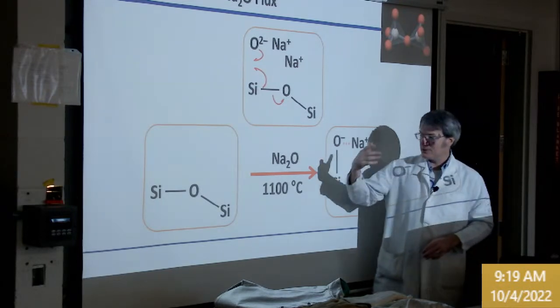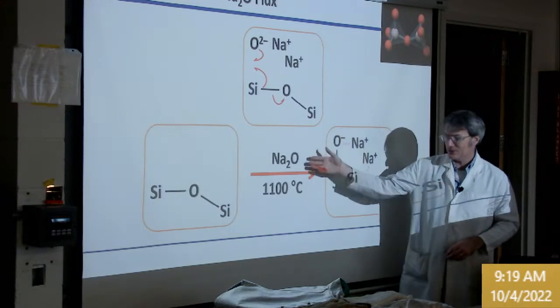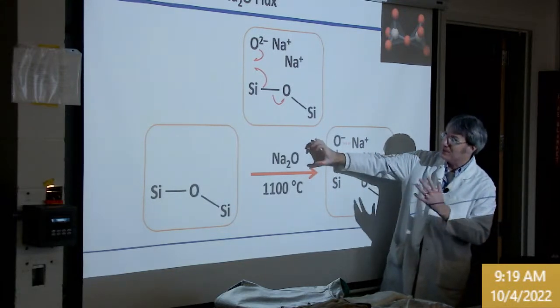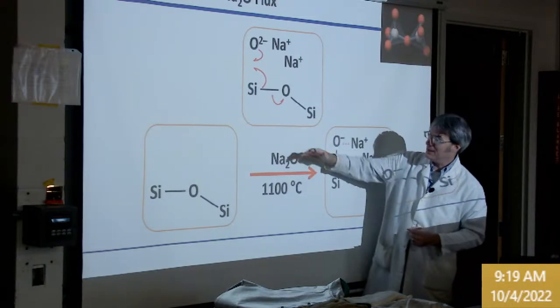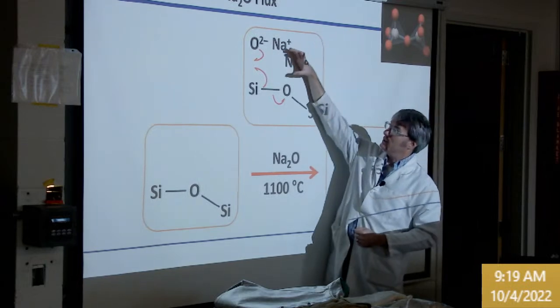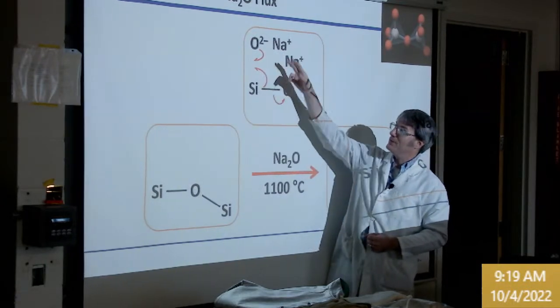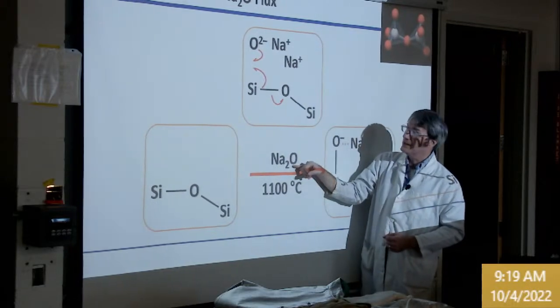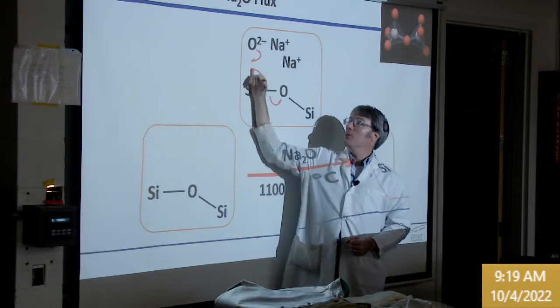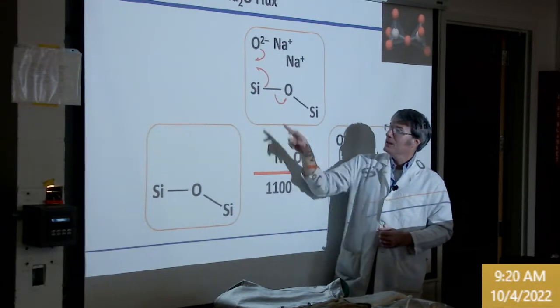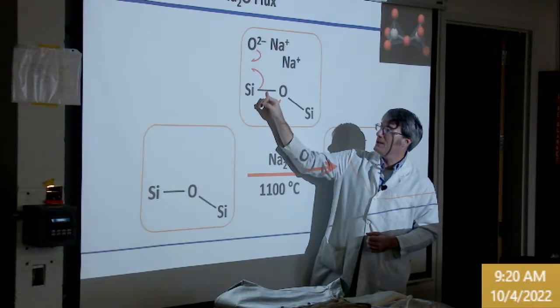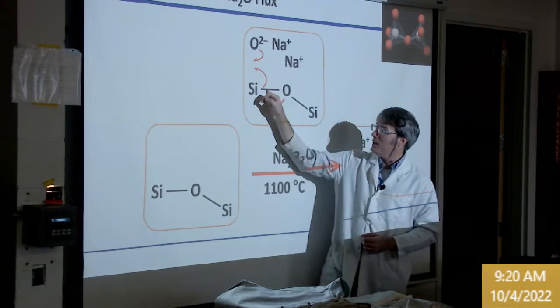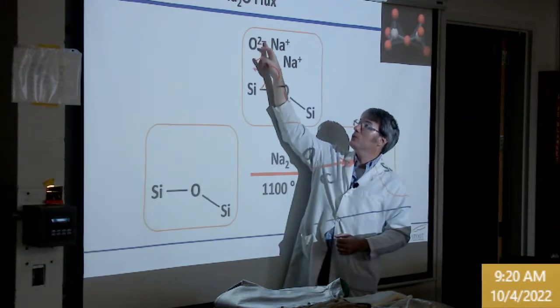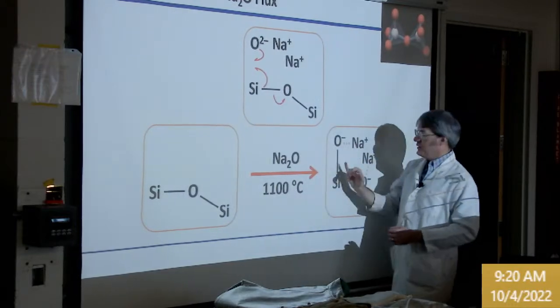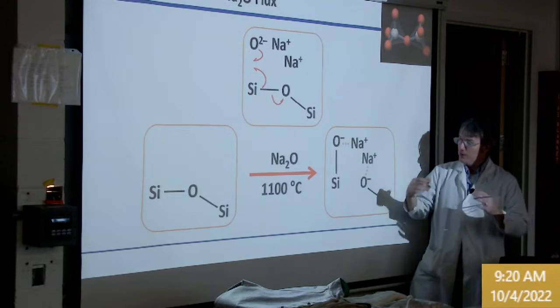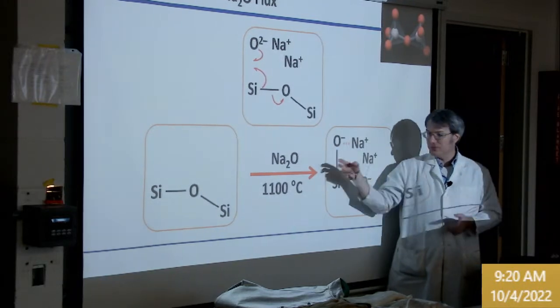Regardless, we off-gassed the carbon dioxide from both the sodium carbonate and calcium carbonate, so we're going to be looking at how the oxides behave. So the sodium oxide at high temperature, when it gets close to these types of bonds, something interesting can happen. The oxygen, the O2 minus from the oxide, is able to reform a new bond with a particular silicon. This is showing one electron events. So remember, each bond is worth 2 electrons. Well, if one electron goes this way, and one of the electrons that was a charge on this oxygen goes this way, well, we can form a new silicon-oxygen polar covalent bond with the oxygen delivered from the sodium.